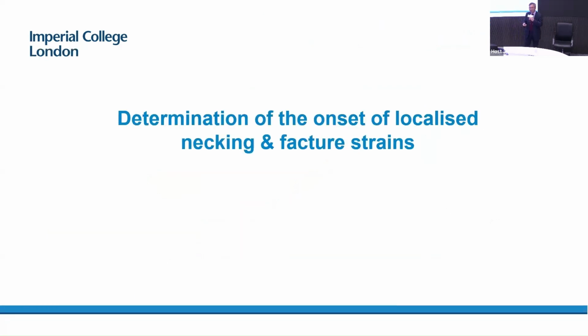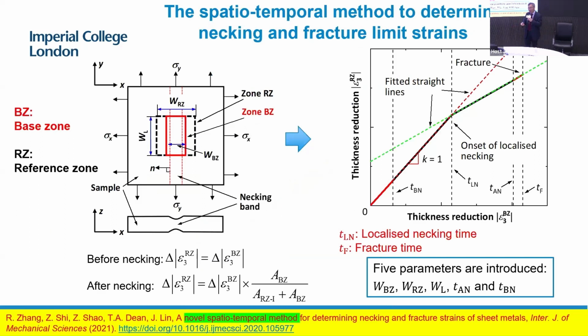And then we need to determine the onset of localized necking. If we stretch the material, as people working on stamping know, one is the necking strain, one is the fracture strain, and people are interested in how to determine the necking strain. We have the base zone and the reference zone. If we plot, for uniform deformation, the thickness reduction would be linear, the ratio equals 1. This is the thickness reduction in the base zone, and this is the reference zone, which would be linear. But when necking occurs, this becomes non-linear. It becomes bilinear.